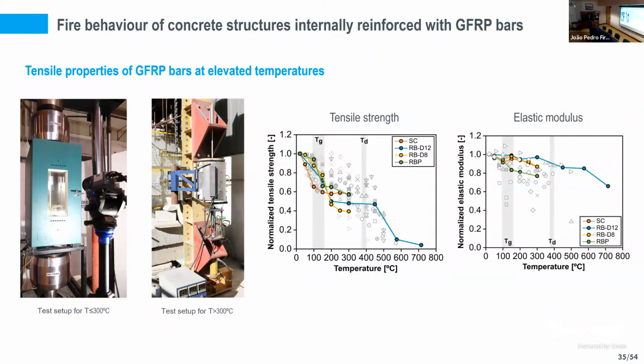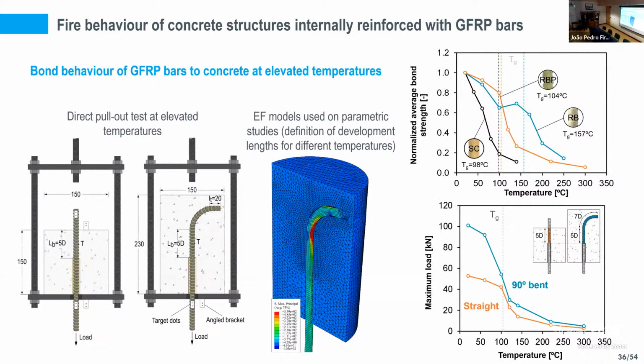On the first scale of analysis, we were able to quantify the degradation of the tensile strength and elastic modulus of the different types of GFRP bars, which is a basic material property that we needed to proceed with this investigation. But the results that were available at that time in the literature were very scarce. And although it seems to be a simple test, it's quite challenging, and we provided very new data to the literature on this topic.